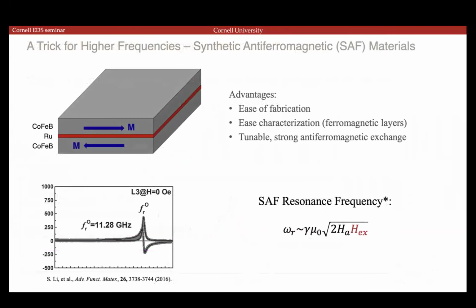And the first approach is to use a synthetic antiferromagnet. So this is using conventional ferromagnets that are easy to grow, easy to characterize, but you just couple them with a thin film of a non-magnetic metal. So in this case, ruthenium. And as long as that thin film is optimized, then as you change the ruthenium thickness, it'll either go between ferromagnetic or antiferromagnetic coupling between these two films. So we can optimize the thickness to get a very strong anti-parallel or antiferromagnetic interaction, which pushes the resonance frequency higher. And this has been shown in the literature already.